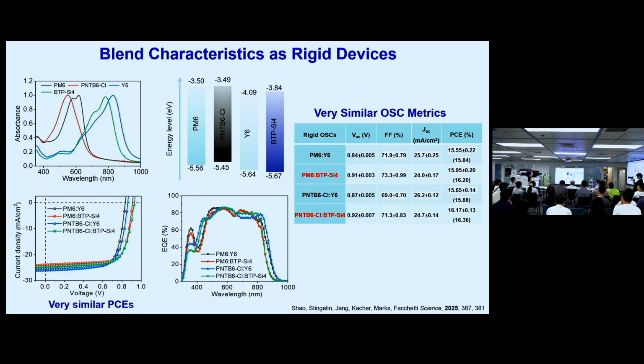And so let's look at some data. And again, I hate to always criticize Y6 or compare against Y6, but let's look, for example, at the solar cell behavior. You put the silicons on there, it doesn't really change the band gap. It doesn't change the HOMO and the LUMOs. So here's Y6, and we're comparing. This is the donor polymer, and here's the silicon acceptor in both of these cases. And the power conversion efficiency is not so different until we apply mechanical stress. And then something really dramatic happens.